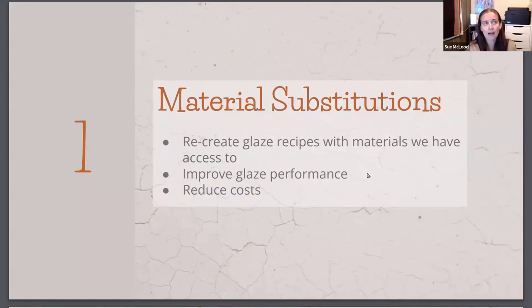So we can replace an expensive material with a not so expensive material, improving glaze performance. Sometimes clay or kaolin is one of our main sources of alumina. You can also get alumina from feldspars, from frits. Depending on which materials you combine together, it'll determine how your glaze stays suspended in the bucket and how the glaze applies to your pots. If we have a glaze that's really low in clay, we might get hard panning. So we could increase the clay content of a glaze, and then we would have to reduce the alumina that we're bringing in with clay or kaolin by reducing one of the other materials. It's a bit of a dance: you increase one thing and lower something else, and then something else goes up. You're always just trying to get the chemistry of the two glazes to match in the end, and then the chemistry in the kiln will be the same.